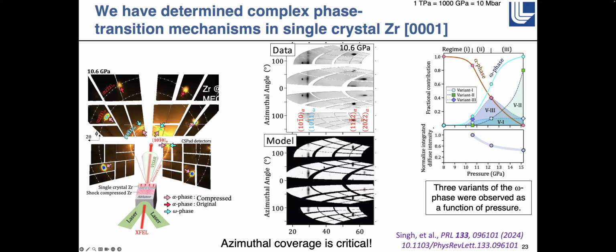And so I'm going to go quickly through a couple of things that we've done. This is in zirconium. We use single crystal zirconium, c-oriented. Zirconium starts off in the HCP phase, and then it transitions to an omega phase. We start with a single crystal where we can't see any diffraction, because we purposely orient our targets so that we don't see any single crystal diffraction. When we shoot it, we do see some driven alpha diffraction.